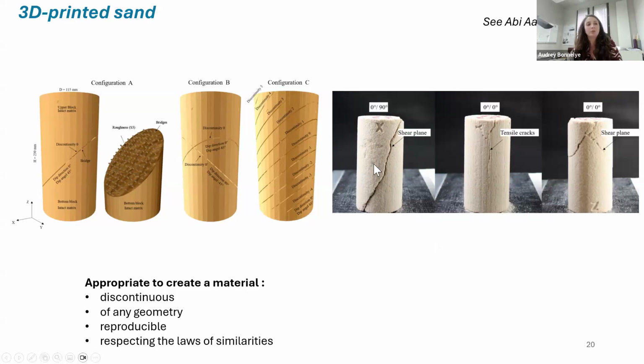And here you can see some tests that he's been doing, those were uniaxial tests. One of the problems of that material is that it has an orthotropic symmetry, which makes it very tricky, let's say, to understand. But one of the biggest advantages is that it really behaves like a sandstone, but with very, very low properties. So it's a very appropriate material if we want to study underground excavation, for instance. And then what we can do is to print some discontinuities, so different sets of discontinuities with various orientations, and reproduce the experiment as many times as we want, if we do have the money, because it's quite expensive.